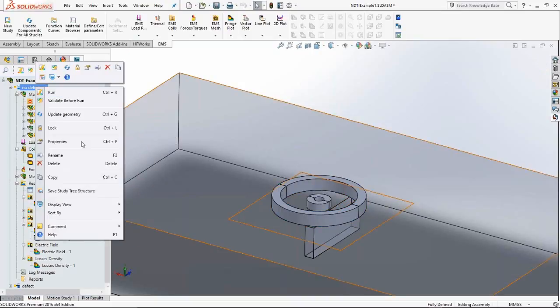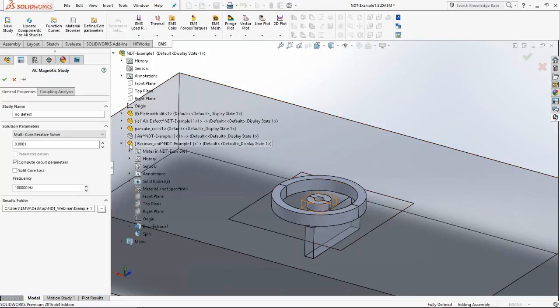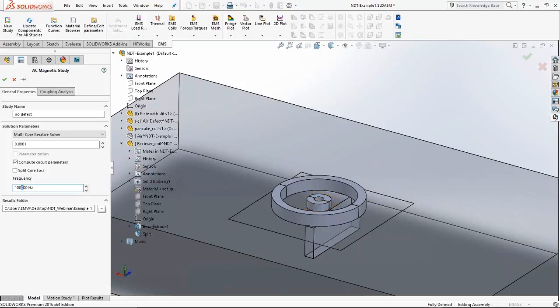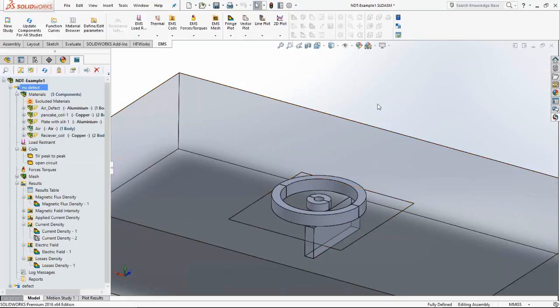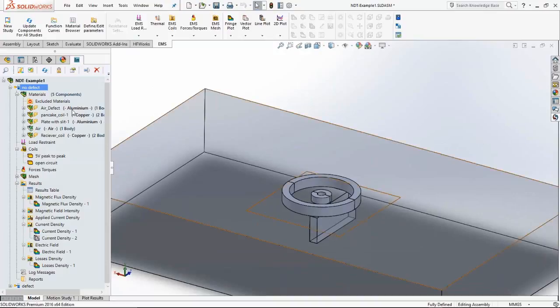Another important parameter is the frequency of excitation. For non-destructive testing, you typically use high frequency alternating current, which allows detection of even minute cracks. The frequency used here is 100 kilohertz. You can run simulations at various frequencies to evaluate how sensitive a given design is. This study represents a normal plate with no defect.